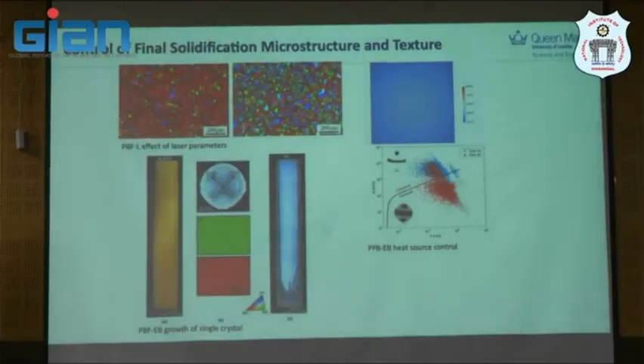If you control it well in the electron beam PBF, someone asked me yesterday about what is the scale. This is quite old now, 2014 or 16. They proved that if you control thermal gradient very well, you can get single crystal in electron beam melting. They didn't say much in detail, but according to private conversation, it's actually just trying to simulate the thermal gradient that's similar to casting condition. Because in solidification of casting single crystal, you will need to control the thermal gradient very well, right?